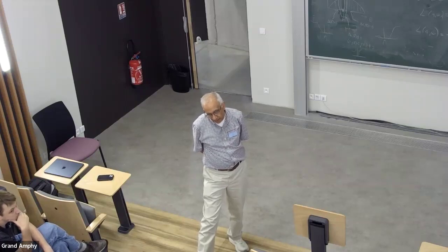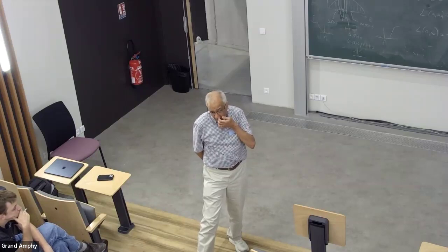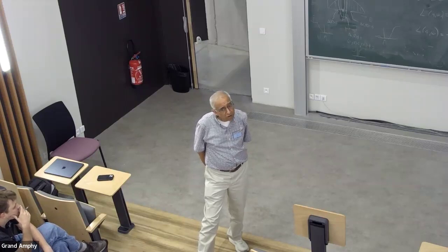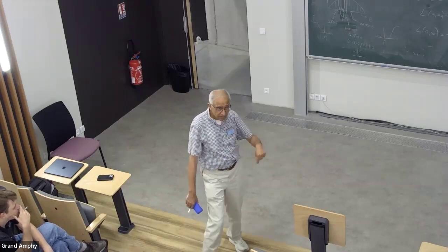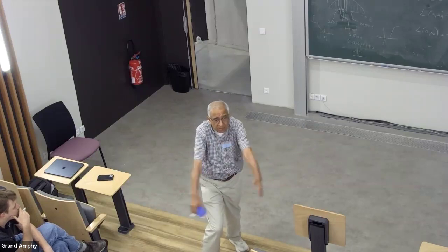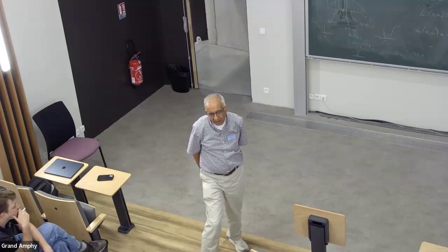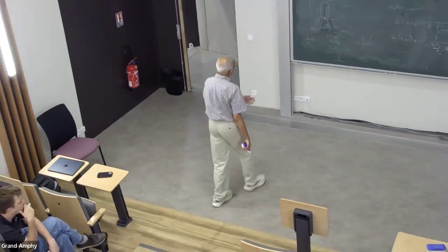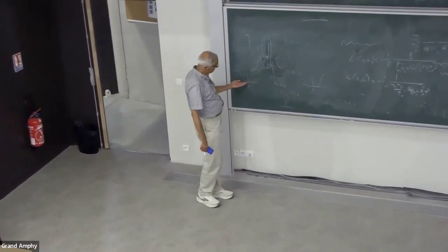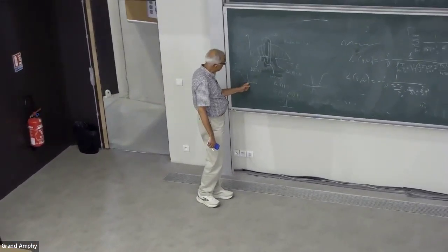So maybe a fair formulation is to say, if we do tunnel spectroscopy, we are always probing the lowest energy single particle excitation. It's not lowest energy. By changing the bias at that location, you can probe all kinds of energy. In case we are talking about this gap, then near zero bias, not about the superconducting gap, but just about the increase in the density of states that we are probing. So if your bias is close to zero, then you're probing things at the chemical potential. That's the way it works.